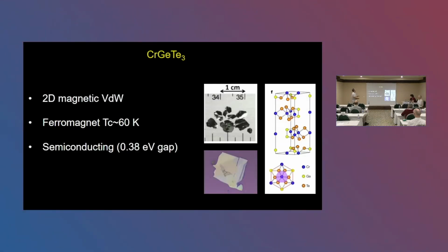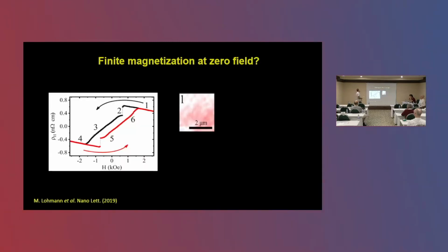So the material I'll be talking about today, the magnetic material, is chromium germanium telluride, or CGT. What you need to know is that it's essentially semiconducting, so it's not conducting at low temperatures. It has a ferromagnetic transition at about 60 K. It's exfoliable, so people look at these flakes. And one of the ways that you can look at these is by proximitizing with a metal and looking at the anomalous Hall effect.